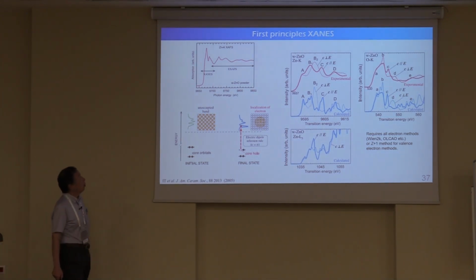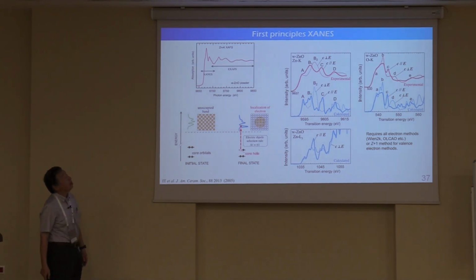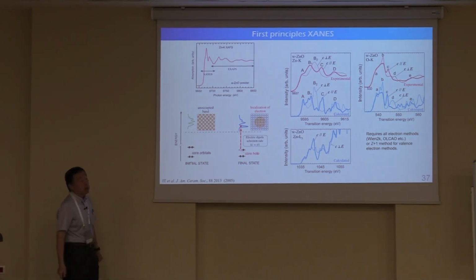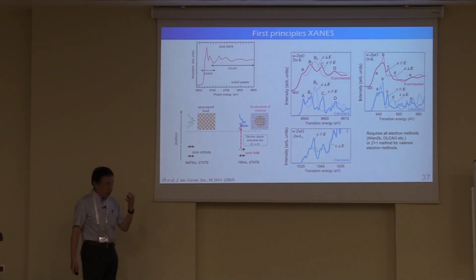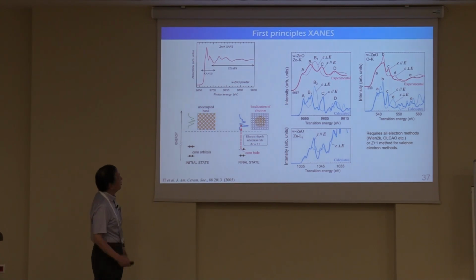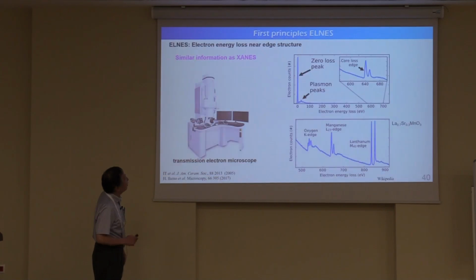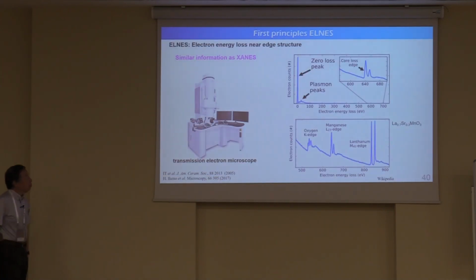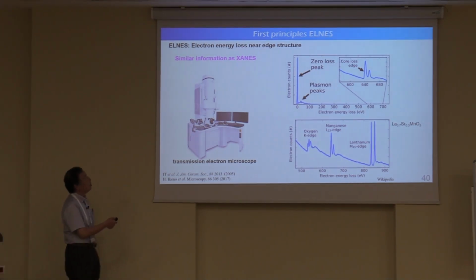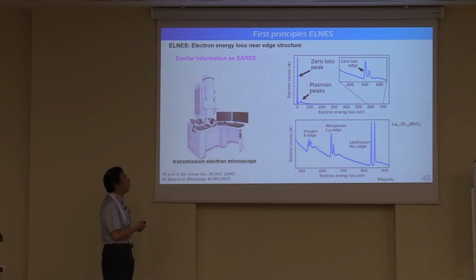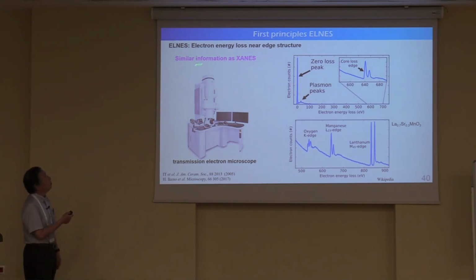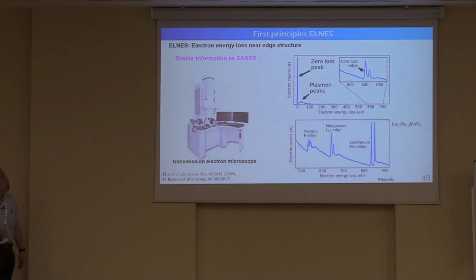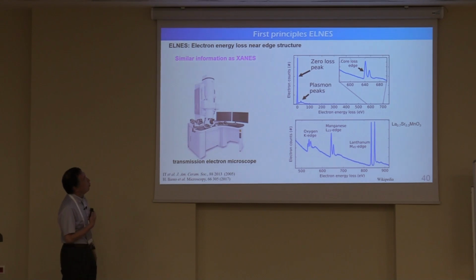I am limited in time, so I will not go into detail, but this is often obtained by synchrotron experiment, and X-ray absorption fine structure is quite useful to get local structure information. It's the same. And also, the modern TEM is quite often equipped with a spectroscope, the electron spectroscopy, and it can obtain information for the electron energy loss spectrum. It is similar information to X-ray absorption structure. So first-principles calculation can do this too.